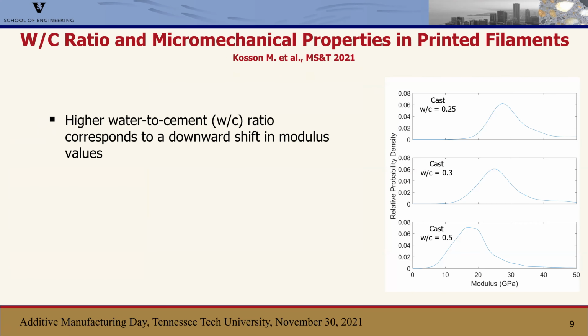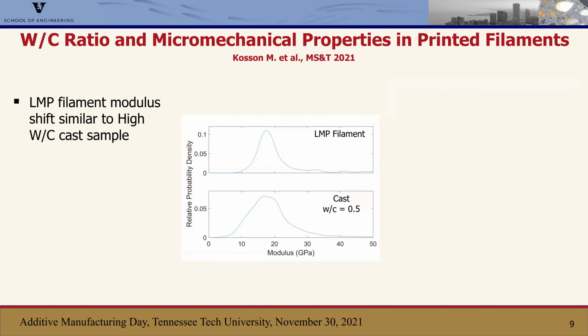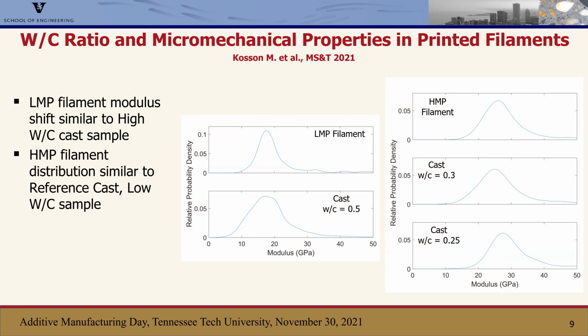So what we found is when we cast samples with different water to cement ratios, we got a similar effect, whereas you have a higher water to cement ratio, that corresponds to a reduction in the mechanical properties of the filaments as measured by nanoindentation. For the low mechanical property filaments, we get a similar effect to what we're seeing when casting with a higher water to cement ratio, whereas with the high mechanical property filaments, we're getting something more similar to casting at a lower water to cement ratio.